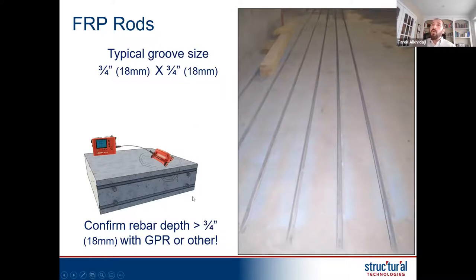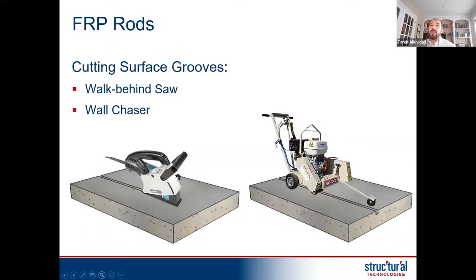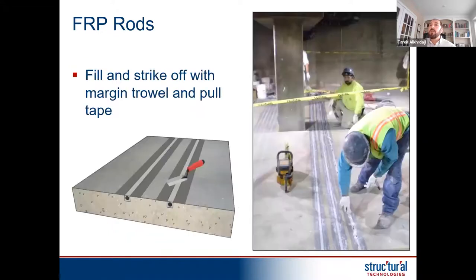However, as always, as part of the installation step, you should always use GPR to locate the bars and verify the depth of the steel bars just in case, because there are many cases I can tell you where the actual depth of the cover is less than what was designed or specified on construction drawings, and these things happen. For cutting, there are many ways that you can do it, like a handheld wall chaser. This is the same saw that's used to repoint masonry, where you can take out some of the cementitious material and put in new grout. Or sometimes there's also a walk-behind saw. So there are many techniques that can be used to cut these grooves.